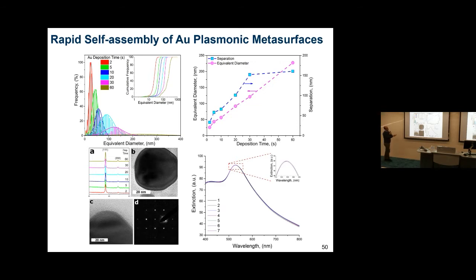The good thing is that they're highly crystalline, so you don't have to do additional sintering to get a faceted structure. If you measure at 7 points across a surface of various square centimeters that we obtain in a few seconds, you'll see that the optical properties are quite comparable.